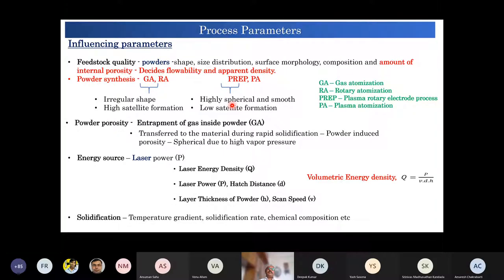Like larger size balls, we can imagine from this point of view that if we pack larger size balls, there are voids left inside it. So to fill these voids, we need to have another size of balls that can fit into those voids, and again there will be voids left. So we need a third size of balls to fill in. So to get a completely dense packing of powders, as required mostly for powder bed processes, we require an appropriate size distribution. And I can tell you as on date, even very good industries, I'm not talking about very niche industries, but most of the cases where people are using powder bed process, they do not take into account the exact requirement of size distribution. And that's the reason most of the cases people are ending up with some amount of porosity.